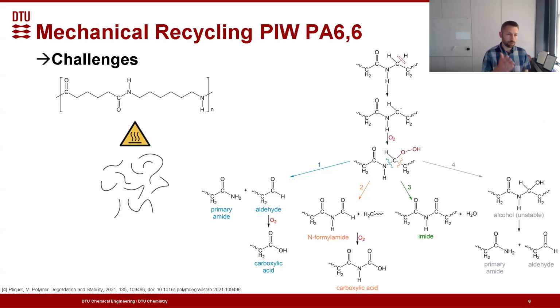If, for instance, as we can see in the first reaction on the top, it's an abstraction of a proton that leads to a radical, and that can then lead to a subsequent range of other species being formed. The first reaction on its own is not necessarily a big problem. There are also antioxidants present that will suppress some of this degradation. But on the other hand, it will ultimately lead to formation of a broad range of different other compounds, which can definitely become a problem later on. If we look at these reactions on their own, they lead to chain scissoring and therefore loss of chain length. Chain length scales with the tensile strength of these systems, and therefore we would expect that we would see a loss of mechanical properties as chain cleavage takes place.